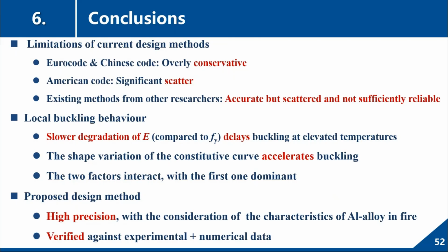And we reviewed the local buckling behavior from our series of tests and numerical studies, including three points. The first one is that the slower degradation of E compared to Fy delays the buckling at elevated temperature. I think this is a new finding based on our research. The second one is that the shape variation of the constitutive curve accelerates the buckling. They are opposite, but the first one is dominant. The third conclusion is that we propose a design method for the cross-section based on our investigations. It is of high precision and considers the characteristics of aluminum alloy at elevated temperature. And our proposed design method was verified against experimental as well as numerical data.